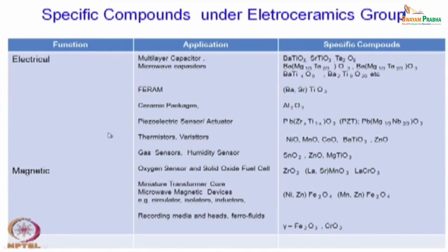Thermistors and varistors are another variety of electronic devices, which once again utilize some of the properties of ceramic oxides. For example, the semiconducting property of nickel oxide, manganese oxide, cobalt oxide, and doped barium titanate. This is not pure barium titanate. If barium titanate is doped with some amount of other oxides, it can be semiconducting. So, these can be used as what we call thermistors, where the resistance changes quite significantly with temperature. A varistor is another variety of material where the resistance changes with voltage, and that again has a very important application area, particularly for surge protection. The material used for this purpose is zinc oxide.